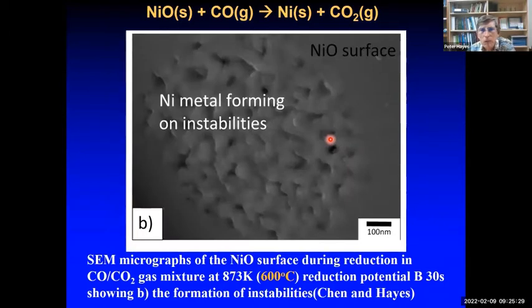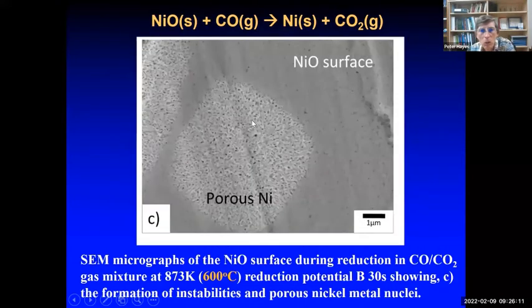If we go for a longer time, there's something strange happening here. We see that the surface, which is initially smooth on the right-hand side here, forms these instabilities or holes. So we spontaneously start to decompose the surface. We see that the surface, instead of being smooth like here, has created these holes or instabilities. And as we go on, these instabilities grow across the surface. You can see one colony over here, another colony here, and some of the faceted holes in the nickel oxide surface there.